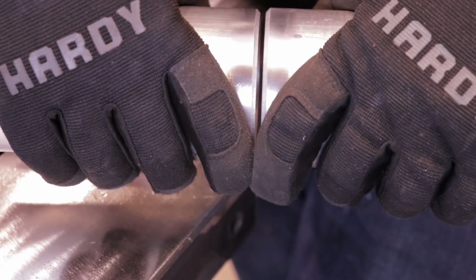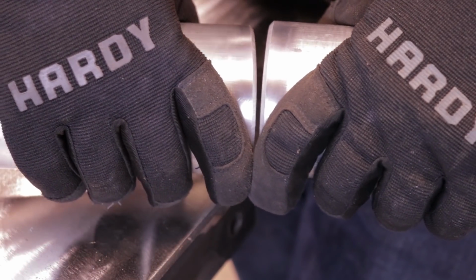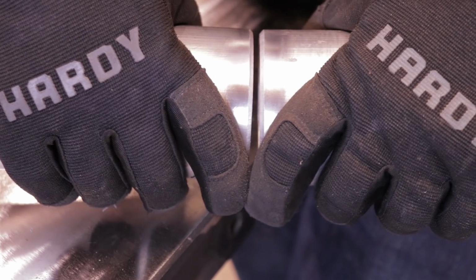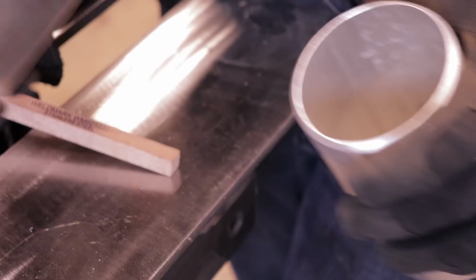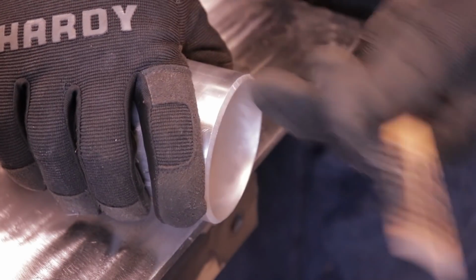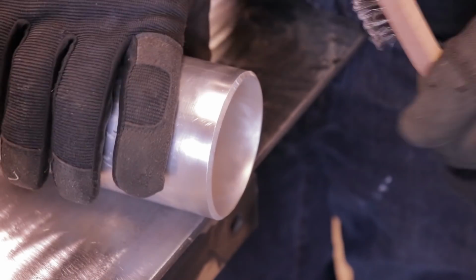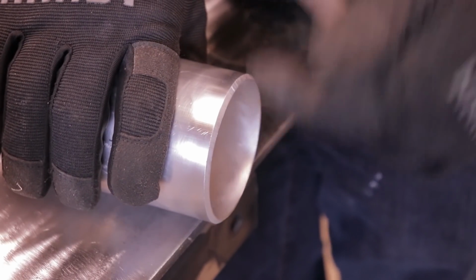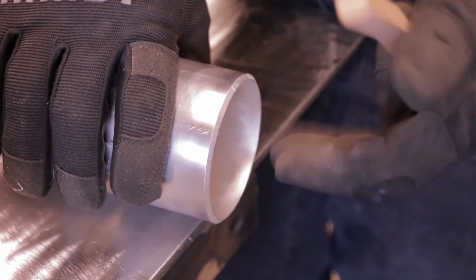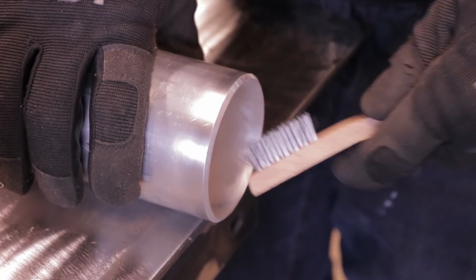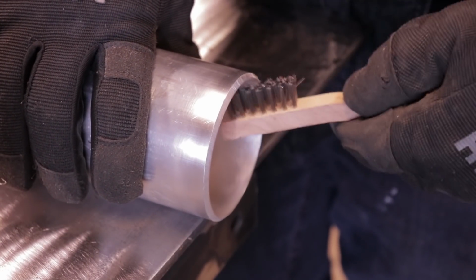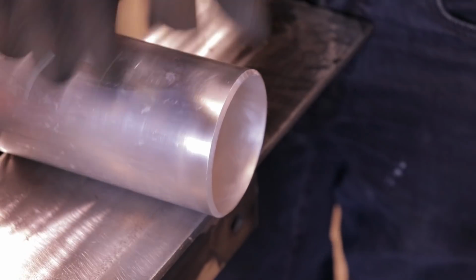Now I haven't personally done it, but when they gap it and weld it like regular pipe, they'll back purge it so you don't get the atmosphere from the other side sucked into your puddle. If you've welded gaps, you'll see a little bit of dirtiness come in, and that's because of the atmosphere from the backside being sucked in.